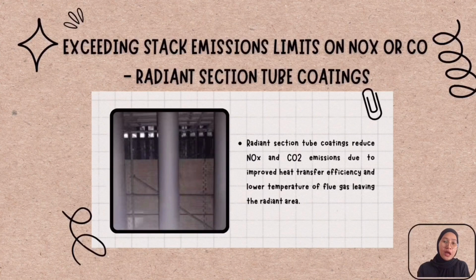High fluid velocity improves heat transfer in the film layer, which lowers the differential temperature between the tube wall and the bulk fluid. Besides that, steam is utilized to passivate the coil surface before the introduction of the feed, by exposing the coil to high temperature steam for several hours. Under these conditions, the synthesis of catalytic coke is delayed and prevented by the accretion of a chrome oxide layer. However, for other coils that have been repeatedly decoked and have a rough surface, this procedure performs less well.